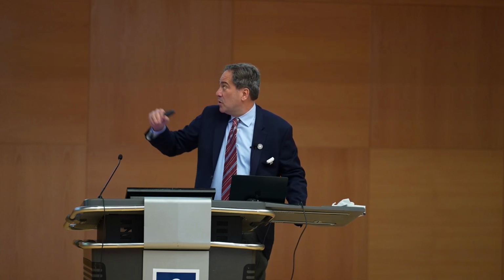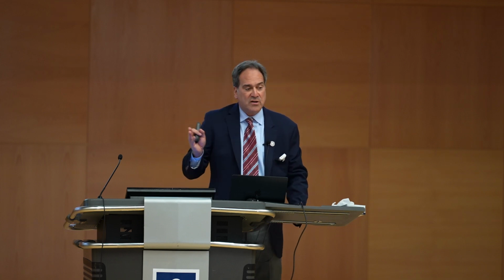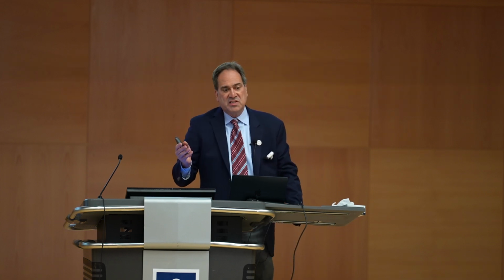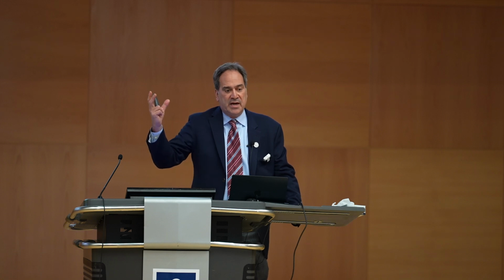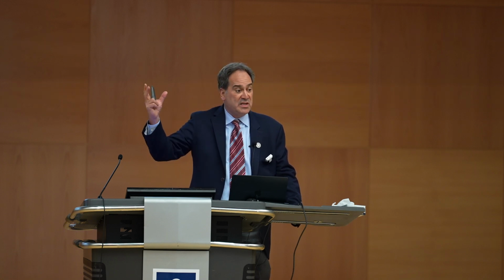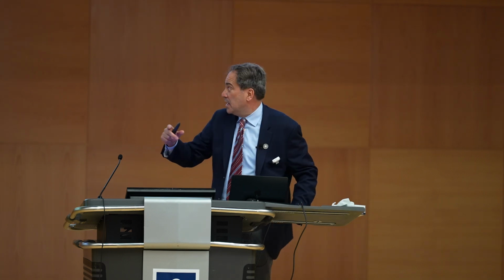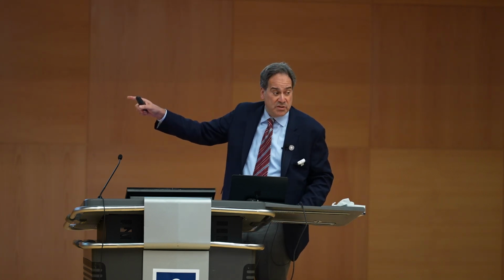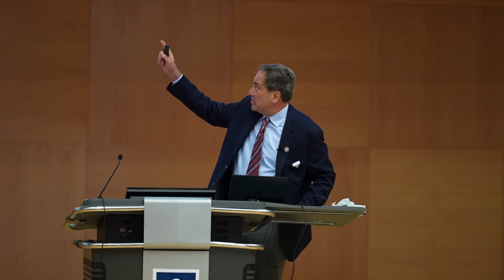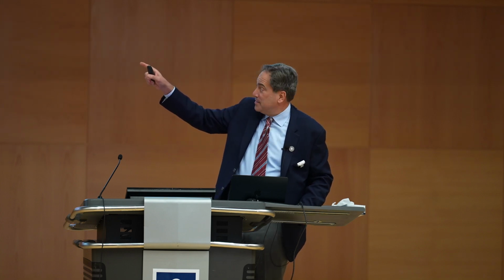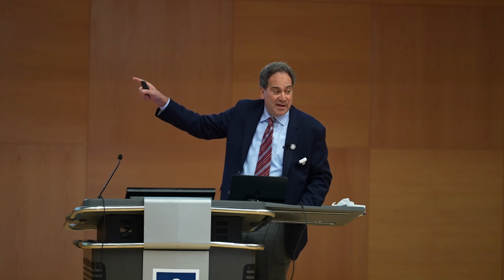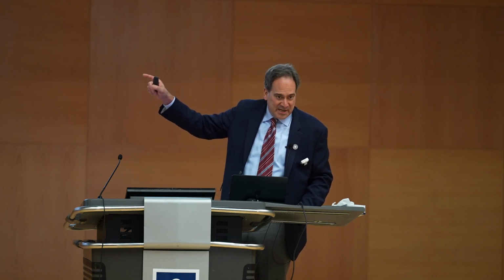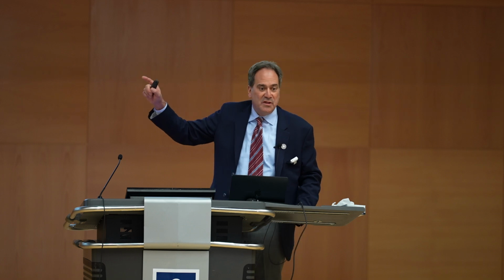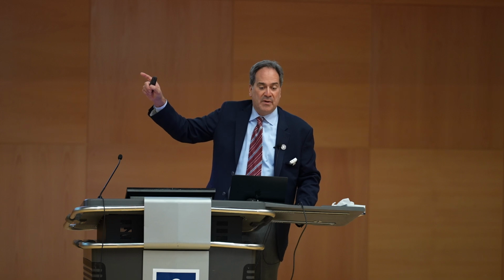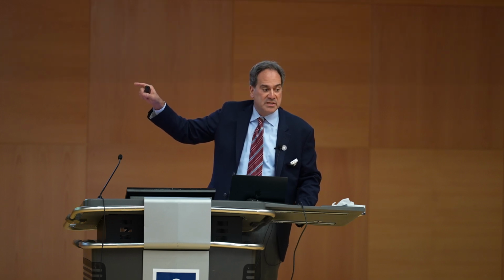So now you can see in the far right here, the reactor size on the left, getting down to 60 nanometer reactor. We have to use dip pen to go to the really tiny features here, just to really push the capabilities. 60 nanometers in terms of reactor size, down to less than 20 nanometers. The particles go from about, call it 6 nanometers in size, down to the bottom one that has roughly 22 atoms. It's less than a nanometer in size. We're pushing the limits of the electron microscope in terms of characterizing. These are aberration-corrected microscopes that are used to characterize these types of materials.